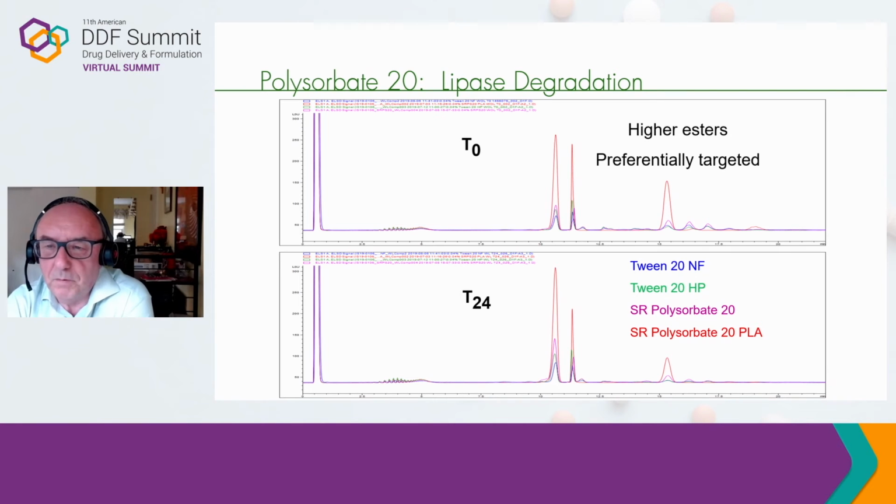In this example of polysorbate 20, we see the same distribution of the peaks irrespective of grade of material, including those found with a pure lauric acid variant we developed for our own research purposes. These chromatograms also show that all grades degraded similarly over the course of the study, essentially commencing with a loss of higher esters and the corresponding increase in the non-alkylated components.